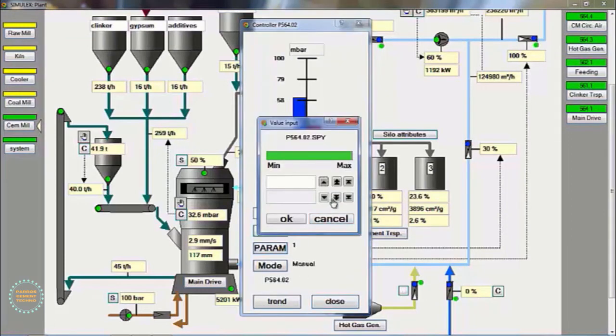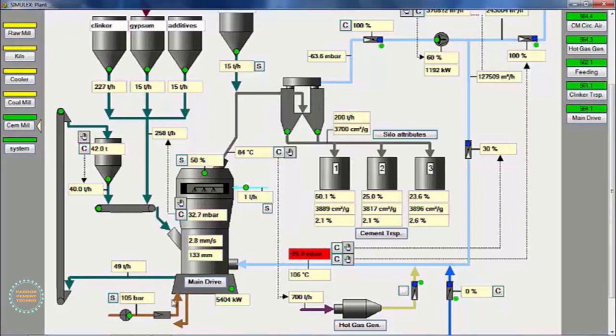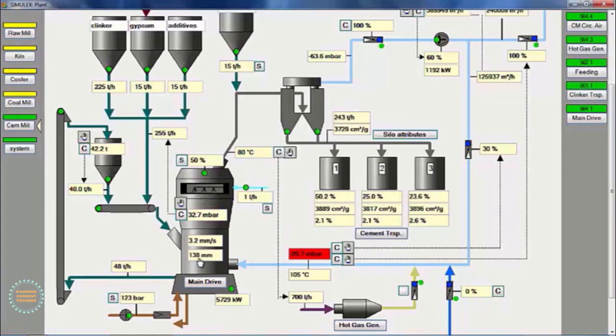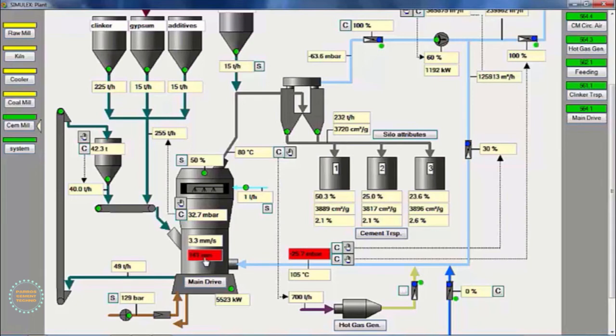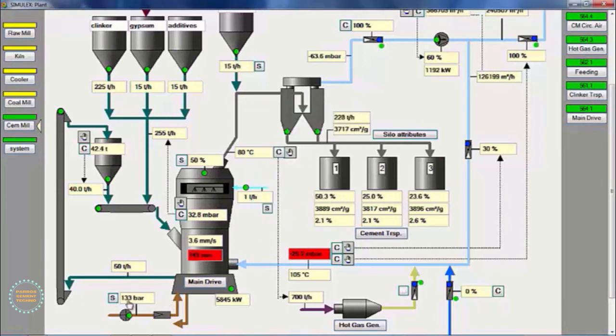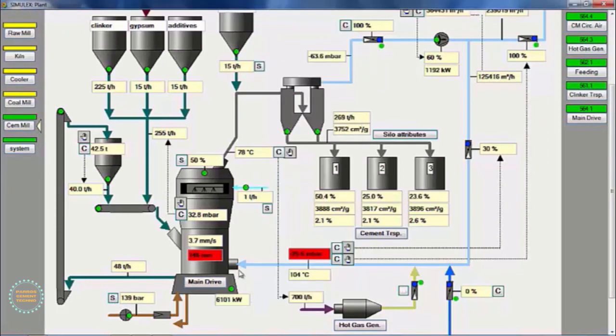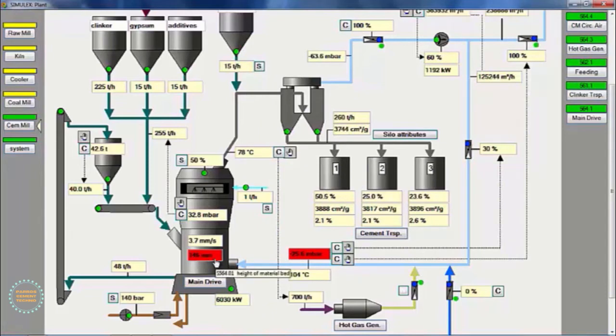Important control parameters in vertical roller mill operation, including: the material bed in the mill is kept between 80 and 120 millimeters, which is controlled using hydraulic pressure. Mill vibration is kept below 4 millimeters per second. Mill vibration is affected by the condition of the bed material. Low bed materials or empty mills can vibrate, and high bed materials or more than 120 millimeters can also cause vibration.